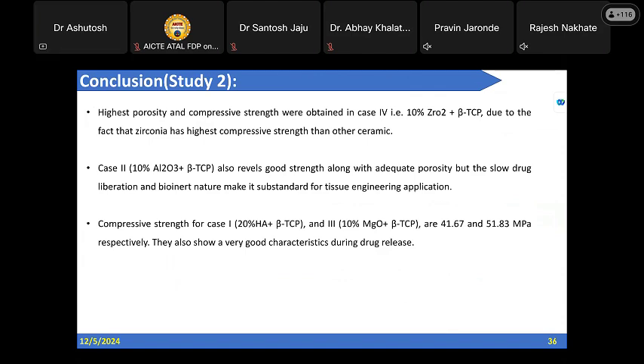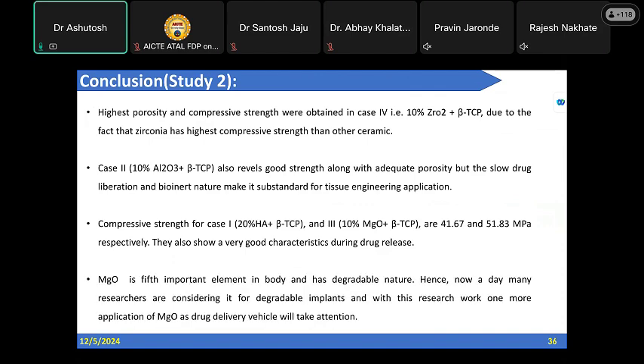The compressive strength of 20% HA beta TCP and 10% magnesium oxide beta TCP are mentioned over here, 41 and 51 megapascal respectively, and they have shown very good characteristics during the drug release. That's why these two parts are taken forward for the animal trial and preclinical studies.